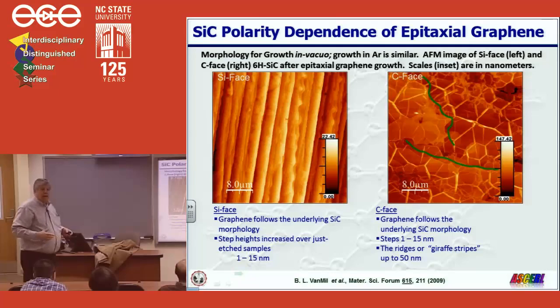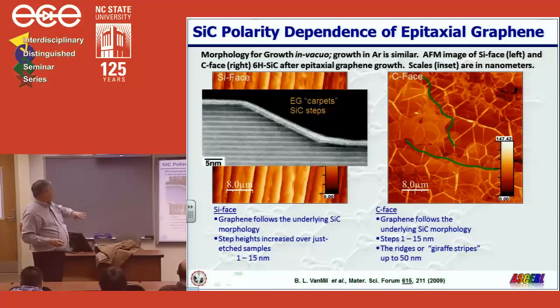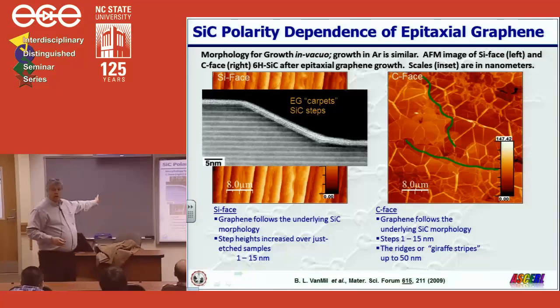And so it's a very rough textured surface. So comparing the two is extremely different. On the left, the graphene grows over the steps, and this is a TEM, and it shows the graphene just going over the steps like a carpet.